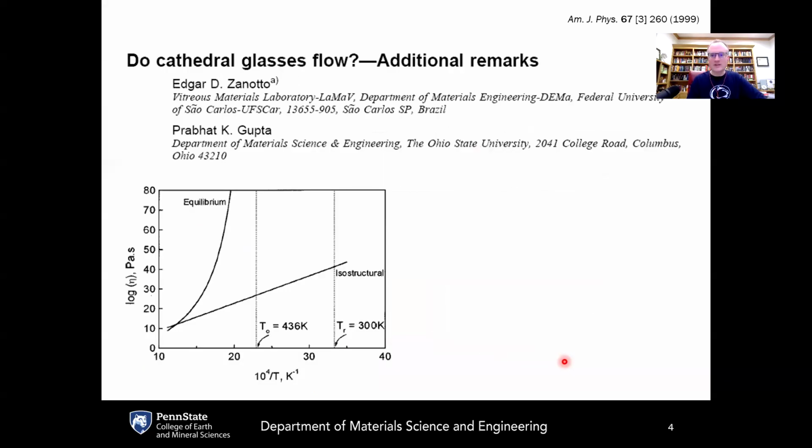So his conclusion was that that's not nearly enough time for the glass to be visually flowing for the cathedral glass, and basically that the thickness variations are just a byproduct of the medieval manufacturing process, which couldn't ensure thickness uniformity, and then it was only natural for the stained glass artisan to put the thicker part of the glass on the bottom because it had at least the appearance of being more mechanically stable.